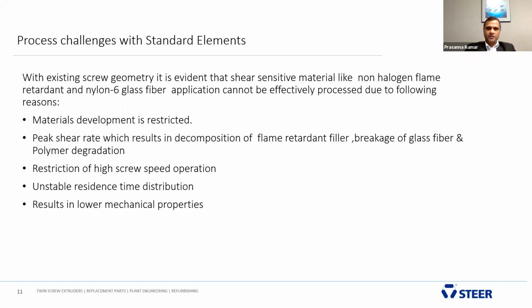Some of the process challenges with standard elements, there might be many more. As a twin screw extruder manufacturer, we have run many trials, and we have listed some of the key challenges. One is that materials development is restricted because of processing limitation. Peak shear results in decomposition of flame retardant filler, breakage of glass fiber, and polymer degradation. Restriction of high screw speed operation.